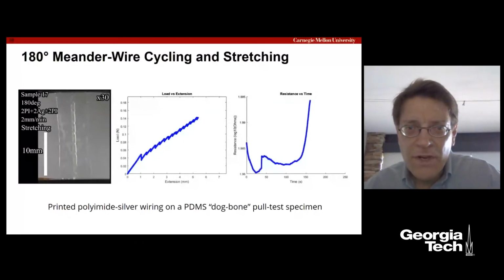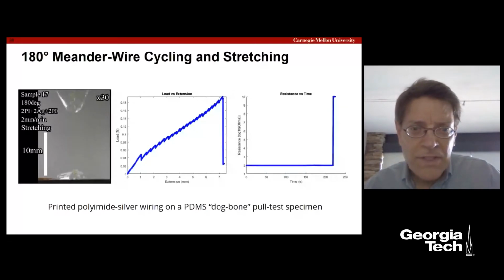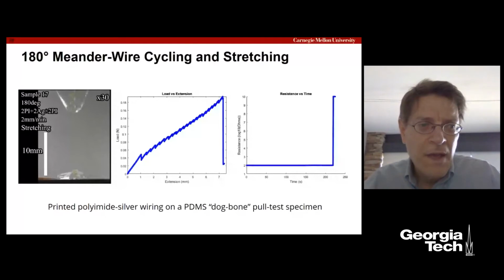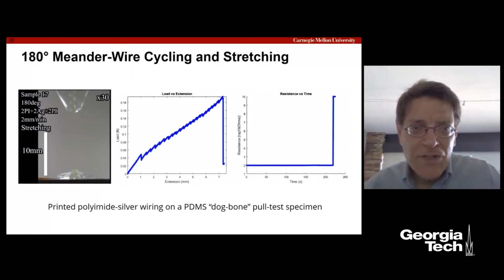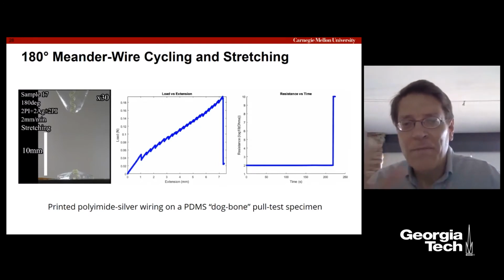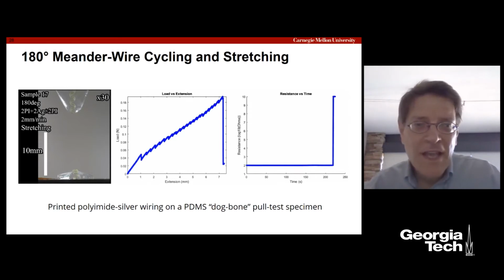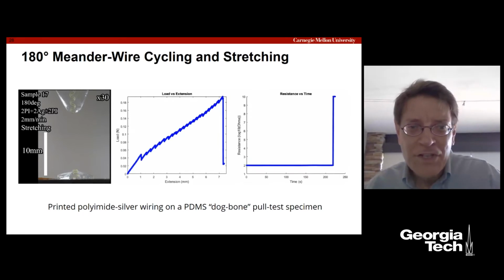You can see here that we get failure at an extension of around 7 millimeters. And again, I don't have the strain on here, but basically that's going to be 3x extension. Notice the jagged nature of the load versus extension, and that's actually micro failures that happen where the polyimide wiring is delaminating from the PDMS in specific locations along the meander, and that starts happening at about a millimeter extension, and then it just keeps popping, if you will, like a zipper.